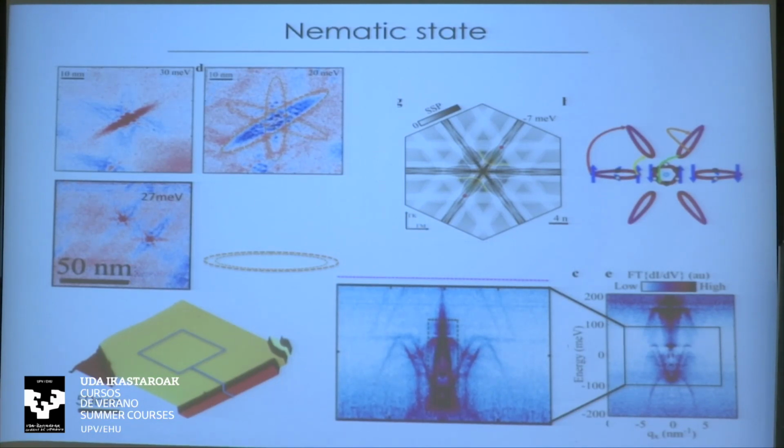And if we now trace back the dispersion, this ellipse structure is basically coming from the wavelength of the electron. By inverting the wavelength to momentum transfer, we can infer also what is the energy separation that we need in order to induce such a difference in wavelength.